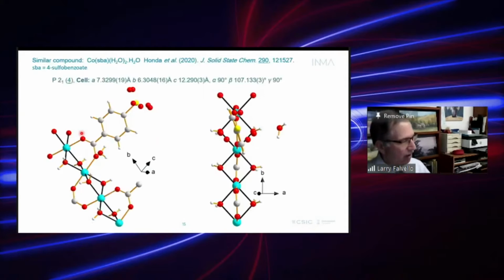And now we go to another compound, which is very similar and was published more recently by Honda and colleagues. And this is also bridged, the cobalt unit with two bridging aquas, bridged by sulfobenzoate. Now, this looks a little strange because the three oxygen atoms are disordered 2 ways each. But this makes the polymer itself neutral, whereas ours was a positively charged polymer and required that extra benzoate to balance charge.